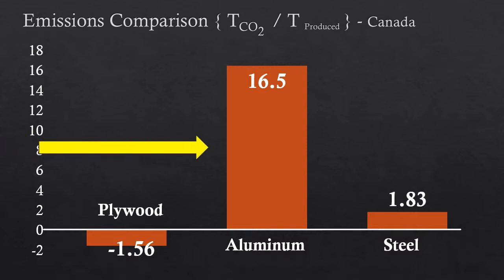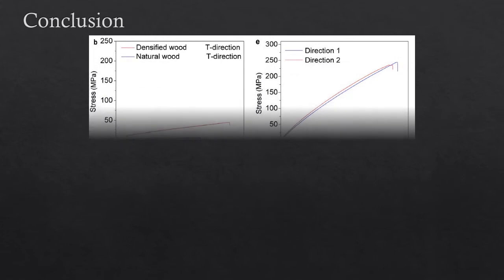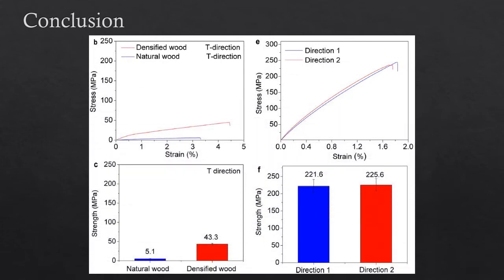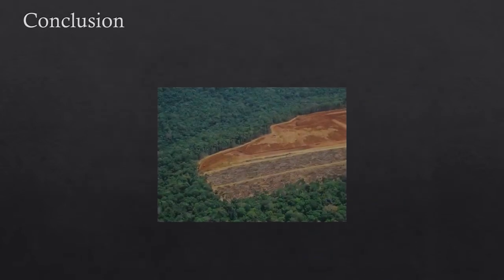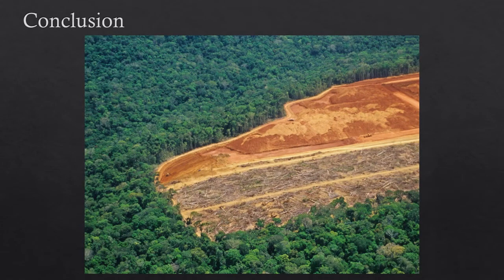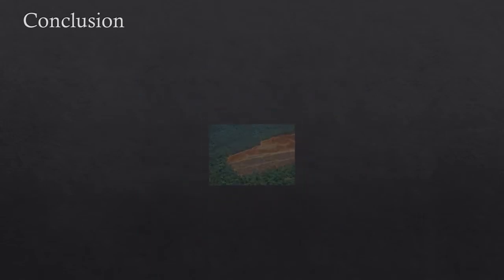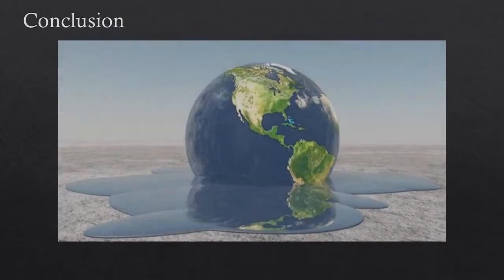When comparing this to the values of steel and aluminum, the difference is staggering. For steel, the average emissions is 1.8 tons of CO2 per ton of steel, but for aluminum, the average emissions is 16.5 tons of CO2 per ton of aluminum. While the material properties of densified wood are good, and the decrease in carbon emissions is evident, there is still one major environmental concern. If densified wood was to completely replace the world's demand of just aluminum, the amount of deforestation that would happen would be devastating. While it seems that this material can't completely replace our demand for aluminum, or metals in general, it should be considered as a viable option to reduce our greenhouse gas emissions and help stem the tide of global warming.